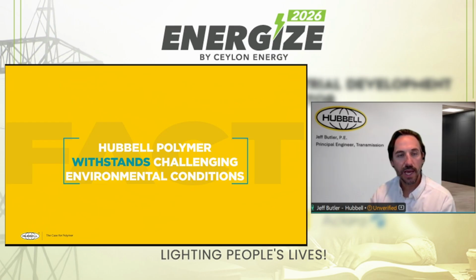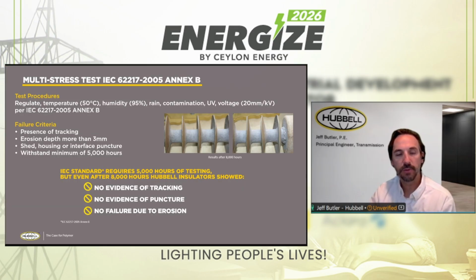IEC has a multi-stress test that was defined back in 2005 in the standard IEC 62217. It's located in Annex B, and it's referred to as the multi-stress test. The multi-stress test controls temperature, humidity, rain, contamination, UV, and voltage exposure. By almost simulating a small field environment, you're able to get a better understanding of the performance of the insulator as if it were out in the field.